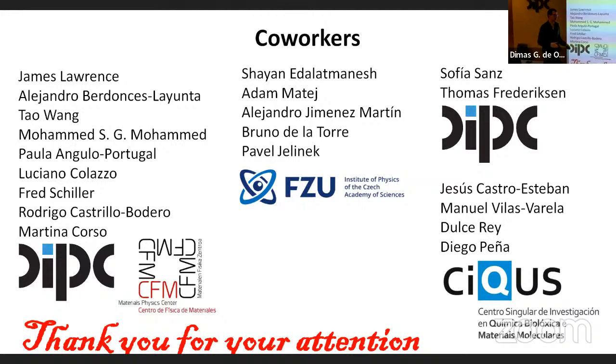I was showing the case of zigzag graphene nanoribbons, which we haven't grown in our lab, but they have been synthesized. So there is only the hydrogen atom saturating the sp2 character of those carbons. But without any hydrogen or other adsorbate, I mean, hydrogen we always have. If you have no hydrogen, then you end up with not only the pz radicals, but you would also have the sigma radical, and those sigma radicals will definitely somehow bind or partially bind at least to the surface.